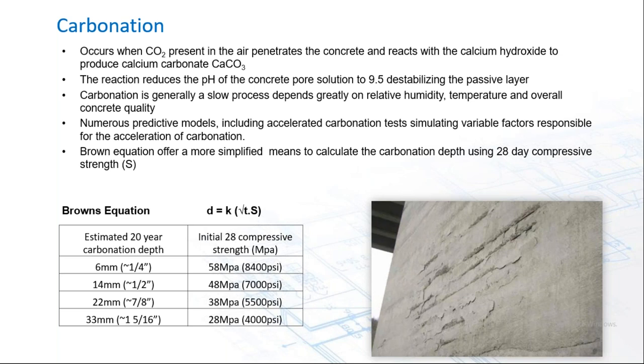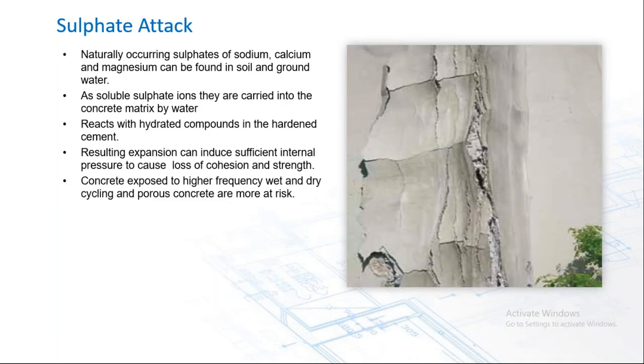we take, let's say, 5,500 PSI concrete, under normal conditions, a carbonation wavefront will extend into concrete just under 1 inch, 7/8 of an inch, in a period of 20 years. Okay, so it is slow, and if that was the only thing that happened to concrete, that's a fairly durable life cycle of a concrete structure. But we're talking about a cumulative effect of a number of other deterioration effects as well.